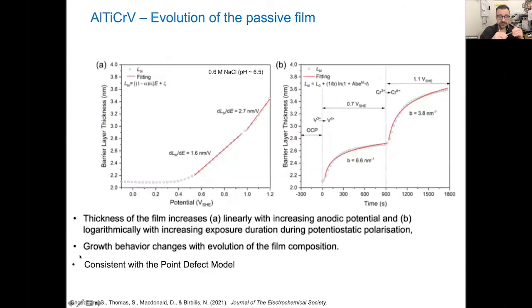In this particular case, we've applied analysis where you do staircase type signals, and it turns out that you can calculate the barrier layer thickness and so forth from electrochemical techniques that are consistent with the point defect model. And it turns out that this high entropy alloy and others, or multi-principal element alloys, I should say, are consistent in their behavior with the point defect model. The growth behavior changes with the evolution of the film composition. The thickness of the film increases linearly with anodic potential and logarithmically with time.